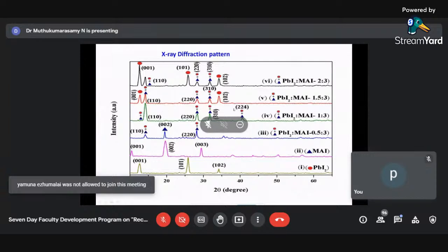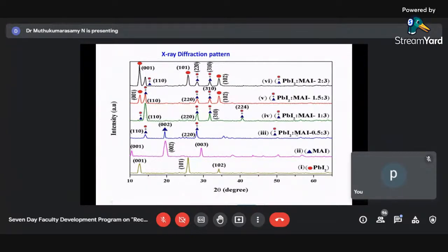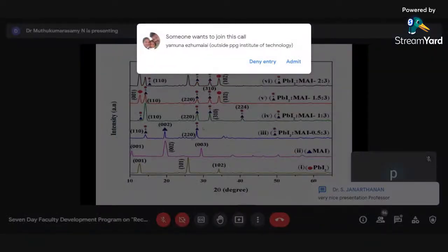You can see here it was only the peaks corresponding to the perovskite material, methylammonium lead iodide. When it was less, you can see the lead iodide peak was also there, the lead iodide 002 peak being present. When we go for excess, what happens? You can see the other one dominating. Excess of lead iodide, other one dominating. Less lead iodide, methylammonium dominating. So 1:3 means we got stoichiometric methylammonium lead iodide.